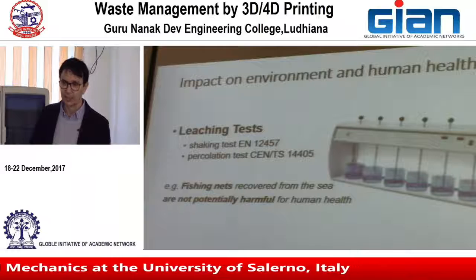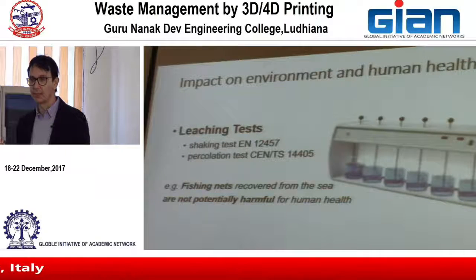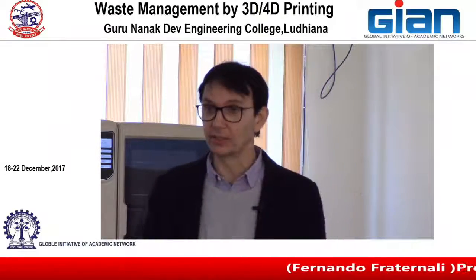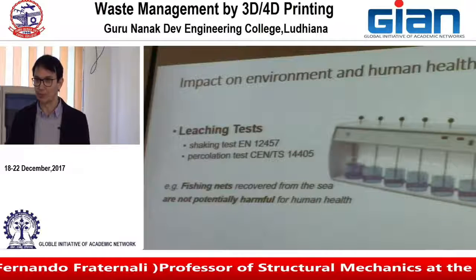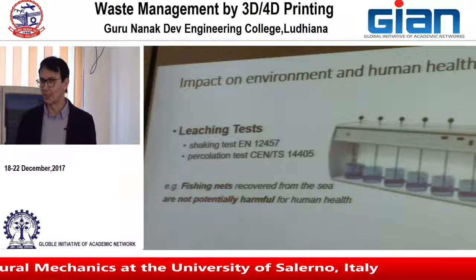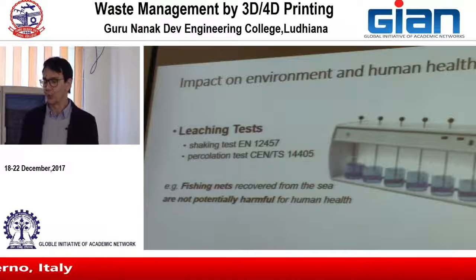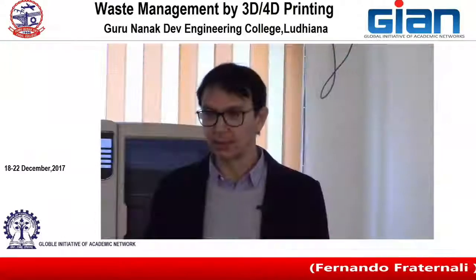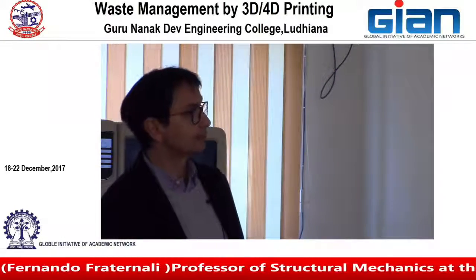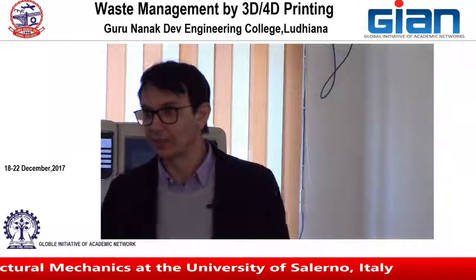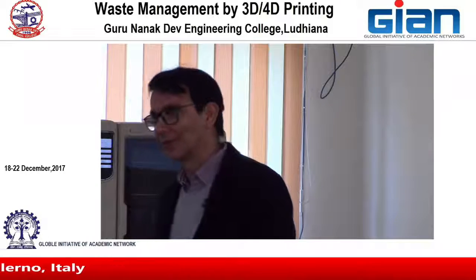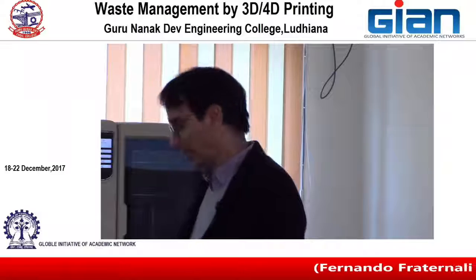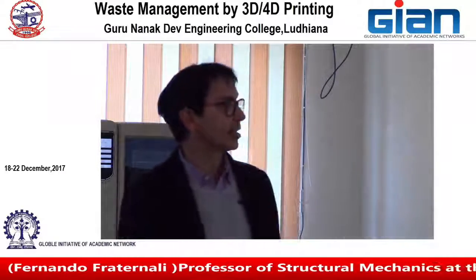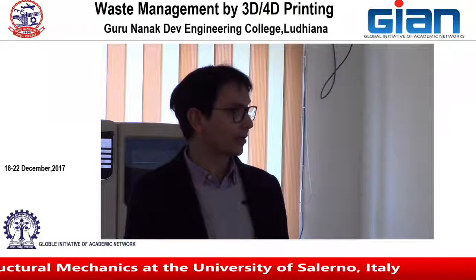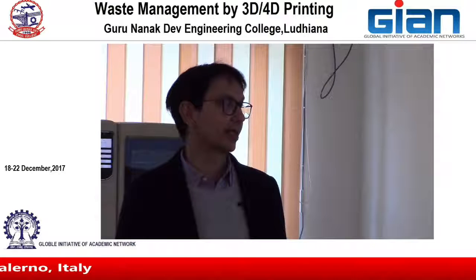You have to measure the chemical nature of the recycled material. You have to carry out leaching tests in order to reuse a material. You cannot just reuse a material without any care. You have to measure the toxicity of the material, because if it is toxic, you cannot reuse it properly. It's not allowed by the standards. Fishing nets recovered from the seas were proven to be not potentially harmful for human health. So they were good candidates for recycling materials.